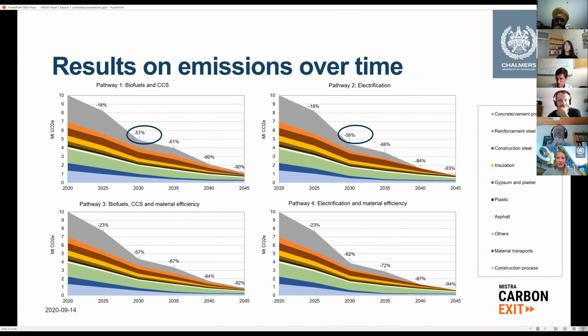So in Sweden, and it's worth noting here, that in the Swedish context, we have generally a low use of alternative binders compared to the European setting. And we also use more cement generally in the concrete recipes. So this potential might be slightly lower in the European context. But we also see a combination of this with energy efficiency measures and other measures in terms of transport and construction equipment being the main sources of emissions reduction potential in the short to medium term.